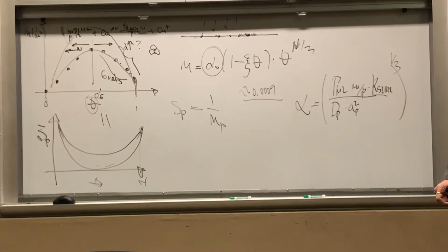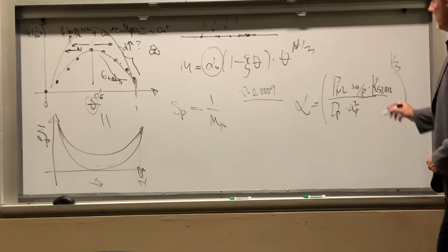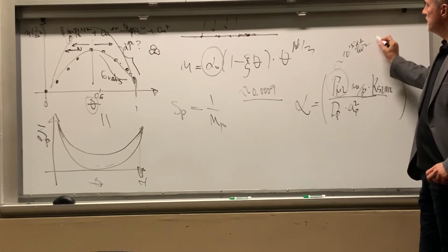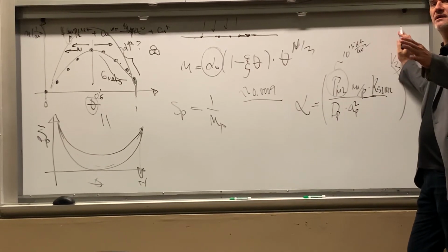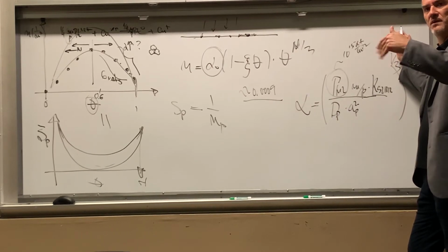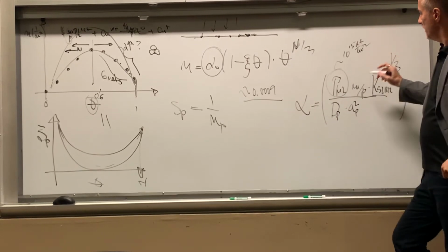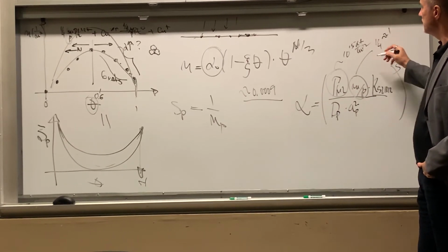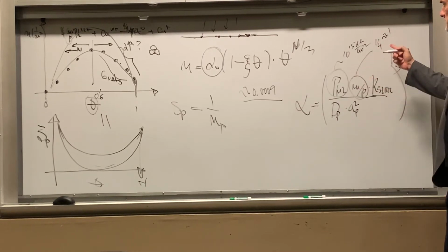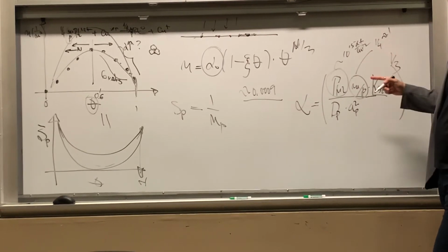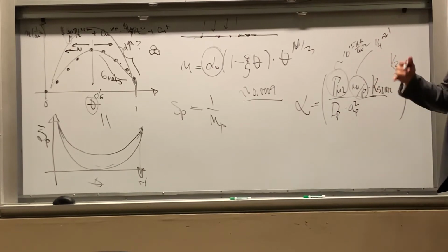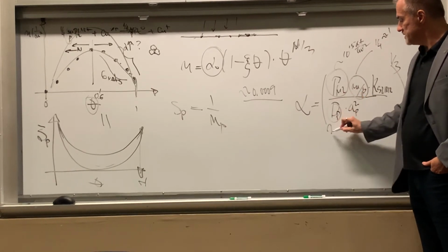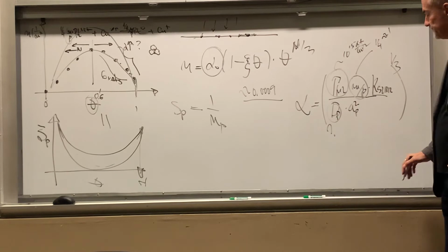The question is, can we control alpha? Obviously, this is of the order of 10 to the 15 atoms per centimeter squared. There's a little change you can make, whether you choose lead, copper and so on. M over P can range from 1 over 4 to 1. So you see this is like a 300% difference, depending on the choice of the UPD coupled with the metal that you're depositing. This I'm going to discuss in a moment, because that's the key of the whole lecture.